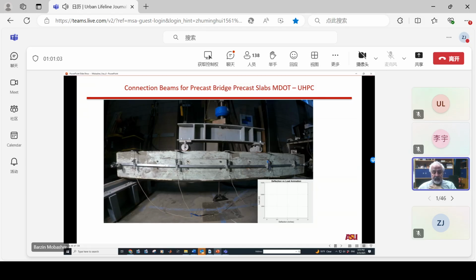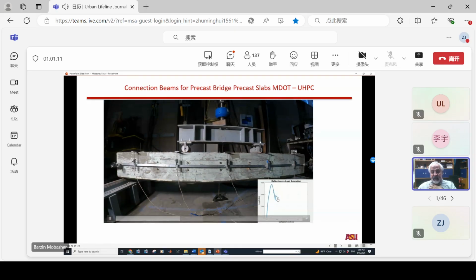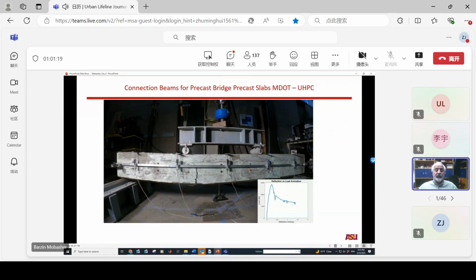Let me see if I can show this video. So this is basically the same UHPC beam that's being tested. And what we can show is that the amount of load that we get basically stabilizes as the crack is propagating. Of course, we're using DIC and all of the tools to be able to show that this residual capacity that we have allows us to reliably expect that the beam is still safe under the load that has been applied onto it.